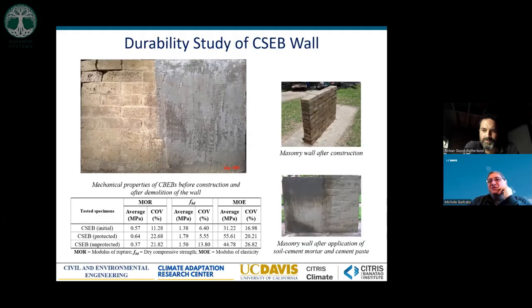So a very simple solution to the technical problem of durability is simply having this sacrificial layer that can be done as we did it with the soil and cement, or more traditionally with the lime plaster, which then needs to be fundamentally just repainted on top every 10 years or so, which is a much lower level of maintenance than having to check every year for termites in our wooden walls.